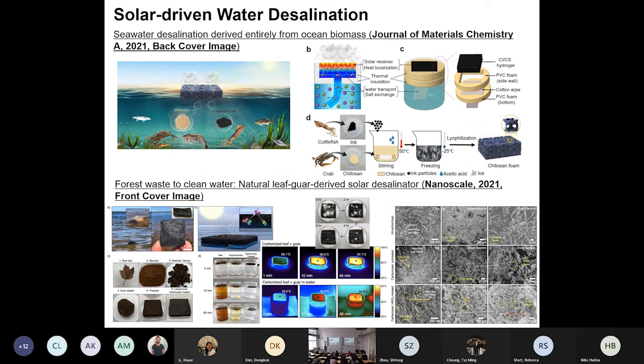Here I want to compare the water evaporation rate for you throughout these four projects. People have studied solar-driven water desalination during the past two to three years. Let's say we have a cup of water, or a tank of water, without any interfacial heating material on top, only going through the natural evaporation process. The evaporation rate is 0.41, 0.42. What is the unit? It is liters per meter square per hour. So per unit time, per one hour, per meter square, it could evaporate up to 0.41 liters of water. Keep this number in mind.